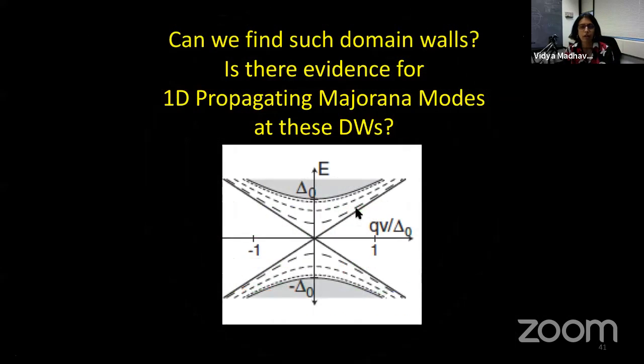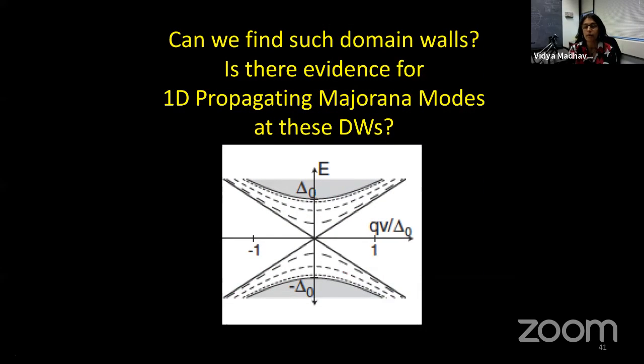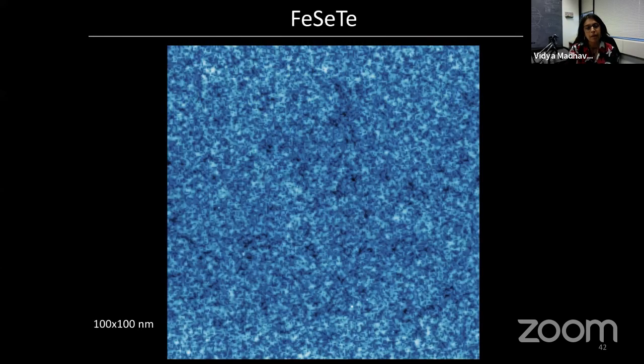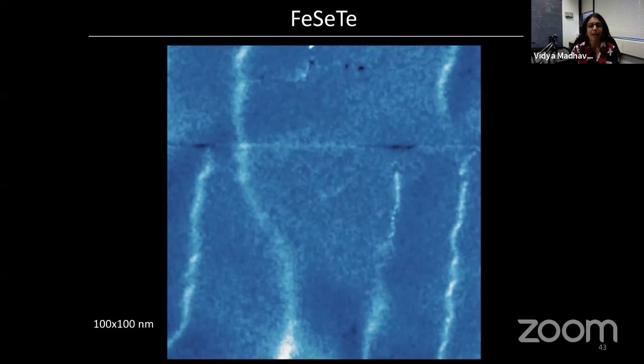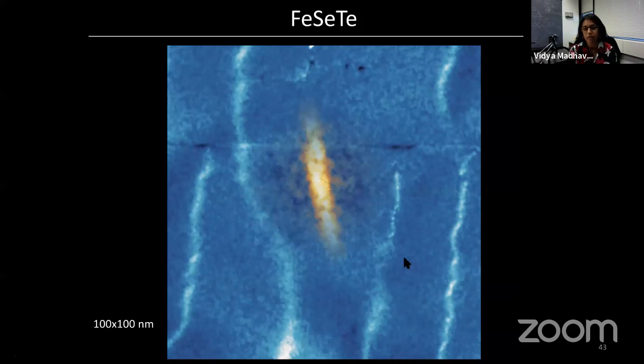So let's just look for these kinds of domain walls and see what we find at the domain walls. This is a pretty large area for STM. It's 100 nanometers, and there are no domain walls in this field of view. But actually, as it turns out, if you walk around the crystal, you can find regions which look like this. And these one-dimensional features are actually domain walls.